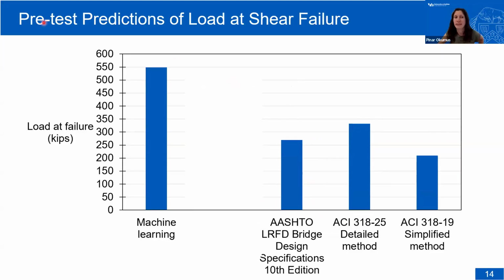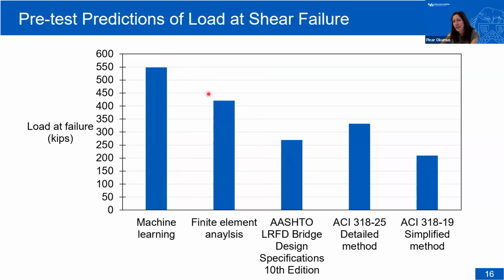Okay, so before we did any testing, we predicted the capacity using various methods. Our machine learning told us that the beam was going to fail at 550 kips, and all the design codes were much, much lower. You can see AASHTO is almost half of it. We also ran finite element analysis on this one, and that's this result. The finite element analysis was in between the machine learning prediction and the AASHTO prediction.